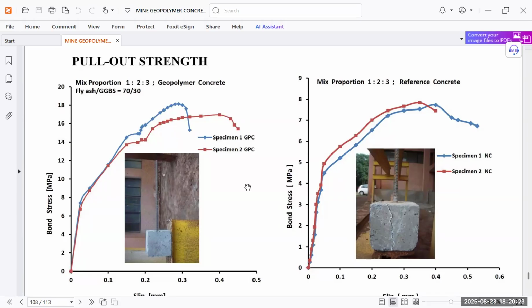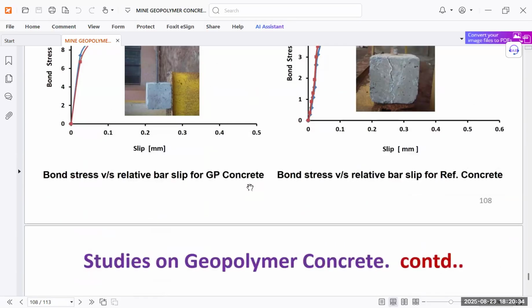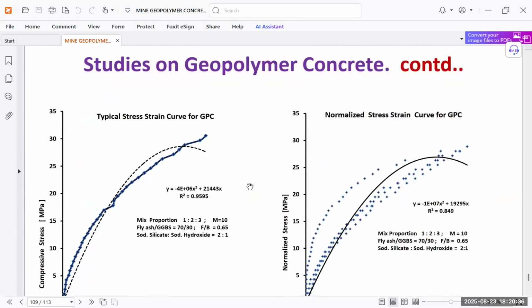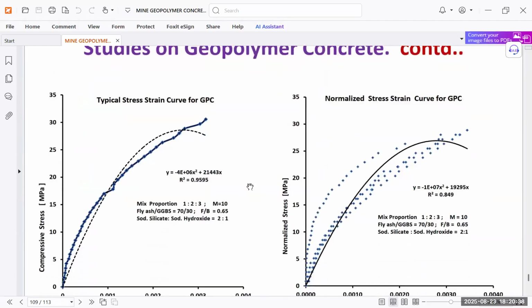So we can see that by varying the fly ash to GGBS ratio, 70 to 30, and making different geopolymer concrete contents, we can change the pull out strength also. And then a typical testing curve has been obtained, and this is the normalized testing curve for geopolymer concrete for different areas. So we can plot it by some regression model. You can see that we have taken, so this is for molarity 10.